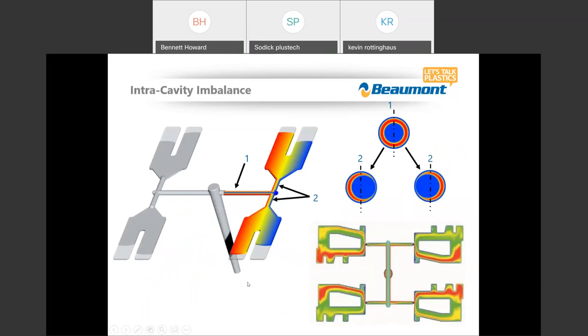I'll do a two-parter here. How we calculate or design our melt flipper geometry that we put in this intersection right here is all based on our sprue inlet and outlet diameters, and then the length of this sprue, and then the length of this primary runner system, and the radius of that primary runner system. So the calculation of the amount of rotation that we put on at these intersections for melt flipper are based on those things. So that shear profile is going to become more intense the longer this sprue.